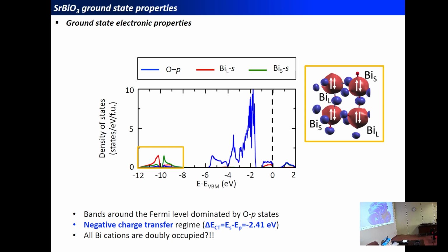This is due to the presence of the breathing distortion that is splitting the two types of cations into two different ones. Nevertheless, if we build the Wannier functions associated with these bands, we end up with 4 S-like Wannier functions centered on the two types of bismuth cations, meaning that very likely these two bismuth cations are similarly occupied. This is not what we expect from the literature, where we expect to have a charge ordering on these compounds.